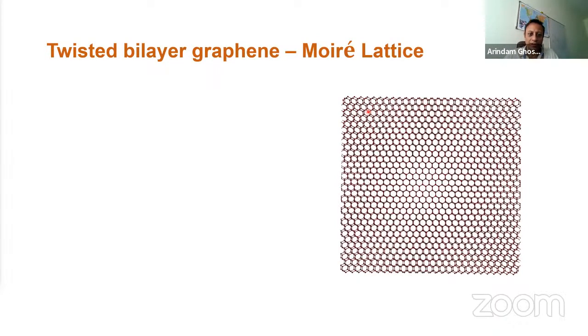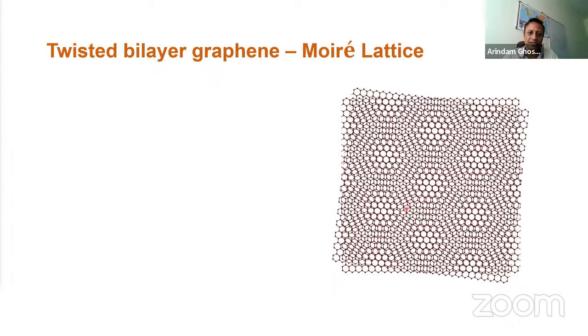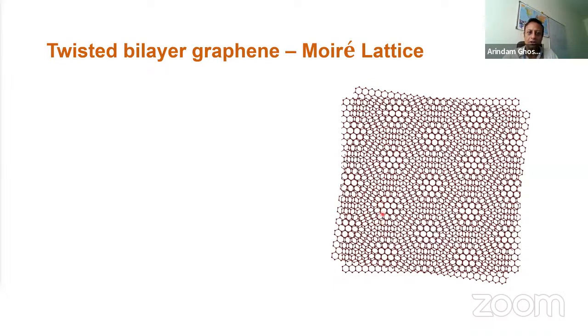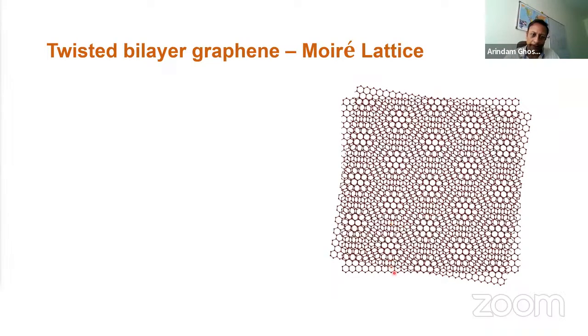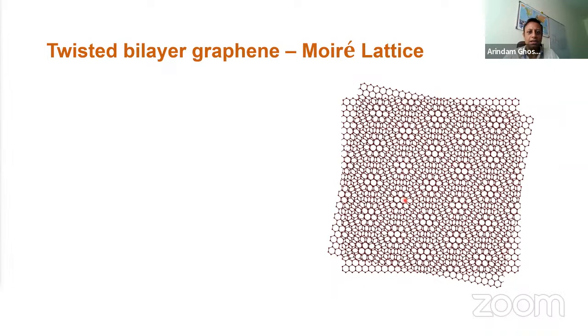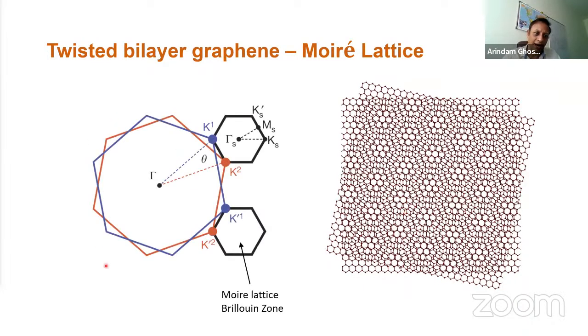You take a mechanically exfoliated graphene and you put another layer on top. And then you start rotating one graphene with respect to the other. And if you keep on rotating, you can see there's a new lattice structure that develops. And this lattice structure is much larger than the single hexagonal crystal structure of graphene. So as a result, this gives a Brillouin zone which is much smaller, and that folds the energy bands and renormalizes various properties of the energy band. And this is called a moiré lattice. Okay? So the basic idea here: you have large graphene bands, 2 graphene bands which are rotated with respect to each other, and you get a very small Brillouin zone, which corresponds to this new lattice structure that has developed as a moiré lattice.